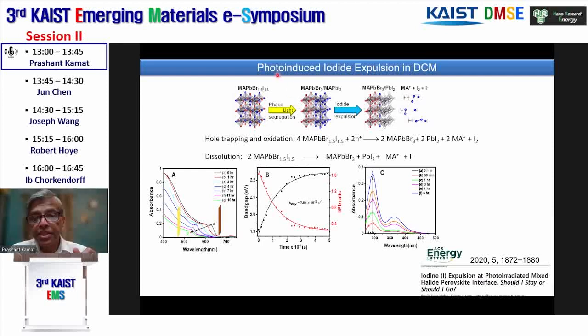So to summarize, what we are seeing here is, in a mixed halide film, when you shine the light, there is a phase segregation first, and the iodide comes to the grain boundaries. And if it is in contact with the DCM, the iodide gets expelled, leaving behind bromide. So it again proves the point that the iodide is the one that's collecting the holes, getting oxidized, and it starts hopping to defect sites, comes to the grain boundaries, and then forms I2, and then maybe grabs an I- from the surface to make I3-.